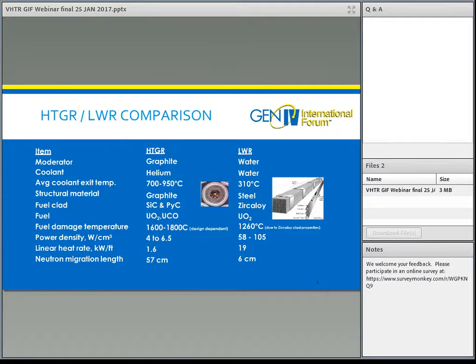Briefly to compare, for those of you who are familiar with light water reactors, how the high temperature gas cooled reactor is significantly different. Probably one of the main differences is where light water reactors use water for both the moderator and the coolant. In a high temperature gas reactor, the graphite, both in the fuel and in the core structure, is used as the moderator, and helium gas is used as the coolant. That helium gas is at a very high temperature compared to the light water reactors, as you see here, up to 950 degrees C in operating experience compared to an average 310 degrees C for water reactors. The main structural material in a gas reactor is graphite compared to steel in a light water reactor.